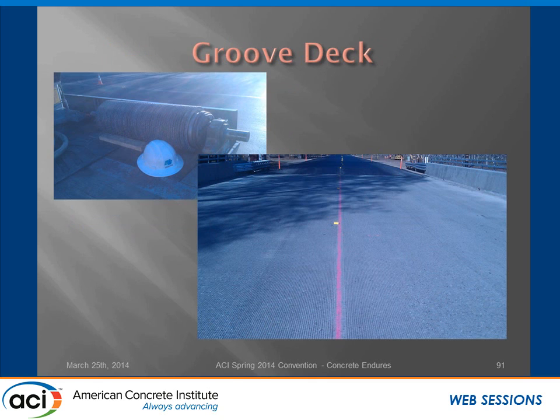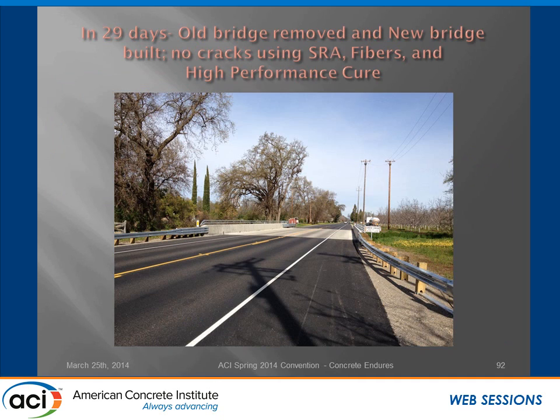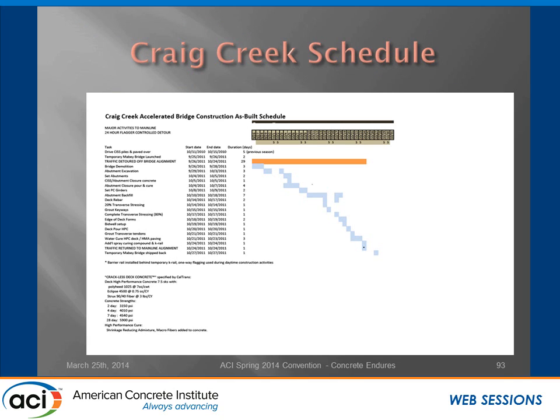So then we grooved it with the grooving tool, and that became a real good, quiet, quality deck. We only took 29 days to take out the old bridge, build the new one, cure the deck, and open it to traffic, which I think is pretty good. I don't think we would have had the success if we hadn't had the shrinkage-reducing admixture and the fibers in there, but it's compatible with the accelerated bridge construction methods.